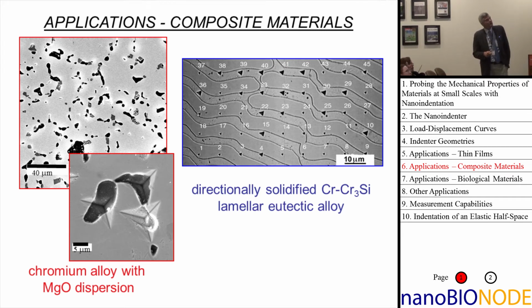Other applications: composite materials, obviously flat material here. This is one that we made. It's a chromium silicide lamellar eutectic alloy. There are two phases in here. This was indented with a Berkovich indenter, and you can see that some of these indents are real small and some of these indents are real big. And these are lamellae in this thing that have a lamellar spacing of about 10 microns.